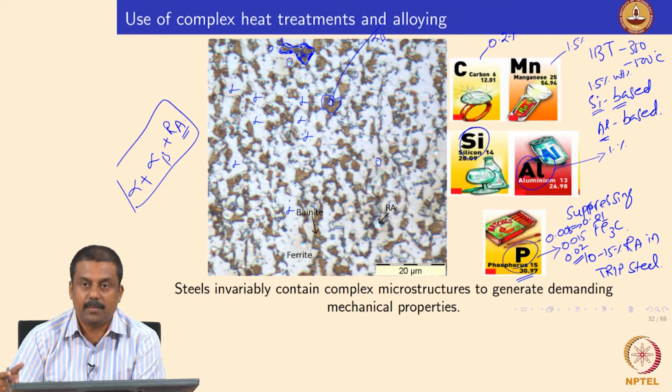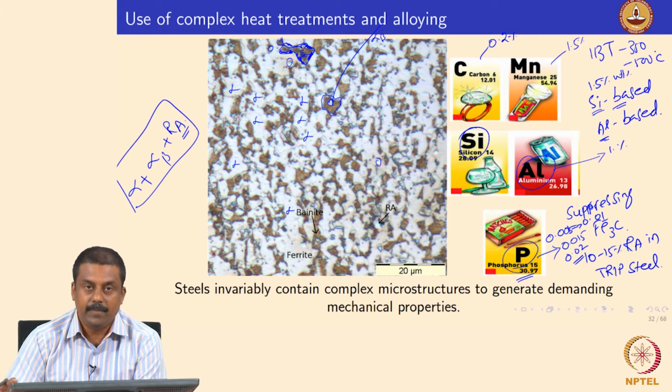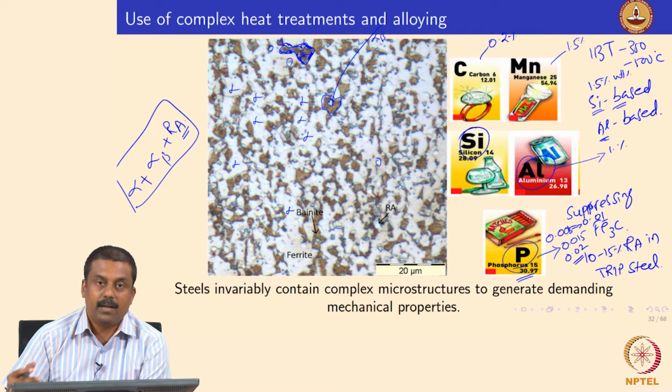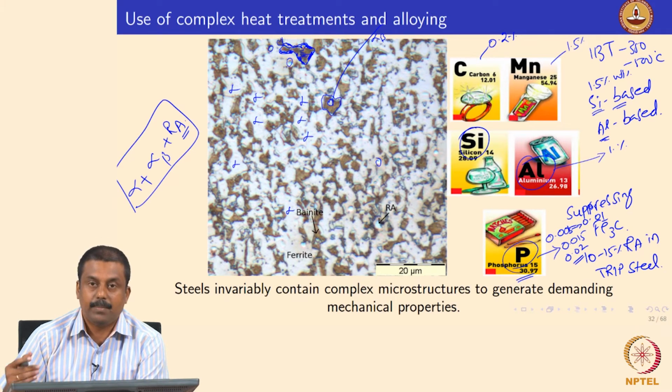During this process, we suppress cementite, thereby enriching the untransformed austenite in carbon, and upon sufficient enrichment, the austenite ceases to transform to bainite. Subsequently, when you cool to room temperature, because of the enrichment in carbon, the Ms temperature decreases significantly and the Mf temperature goes down below room temperature.